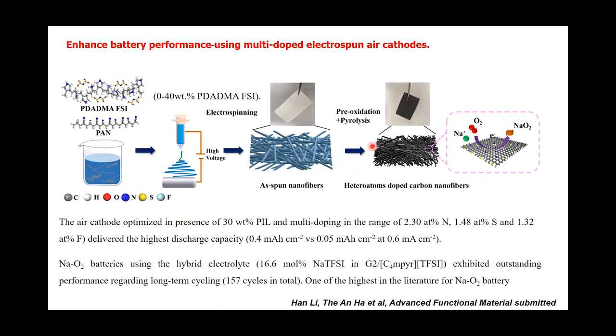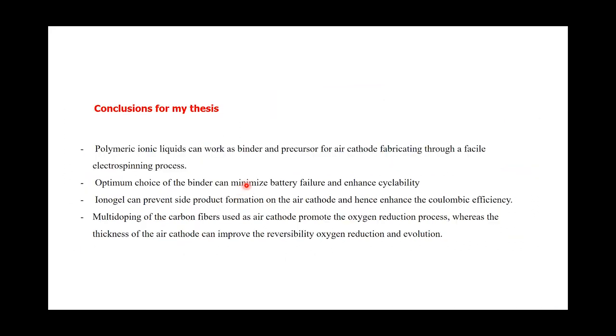Finally, I worked to enhance the long time cycling. We use the multi-doping electrospun air cathode. We use PAN and polydiallyldimethylammonium as the core precursor to synthesize the nanofiber. And we found the air cathode optimized with 30% polymer and a very high multi-doping percentage on top. This air cathode delivers the highest discharge capacity. Moreover, the sodium oxygen battery using the optimized air cathode and hybrid electrolyte shows outstanding performance regarding long-term cycling, over 150 cycles. And I would like to note this is one of the highest in the literature regarding sodium oxygen batteries.